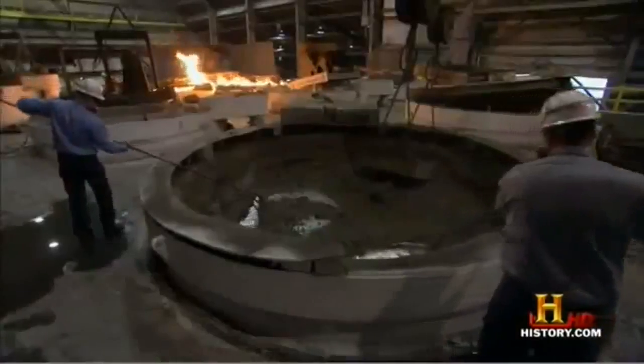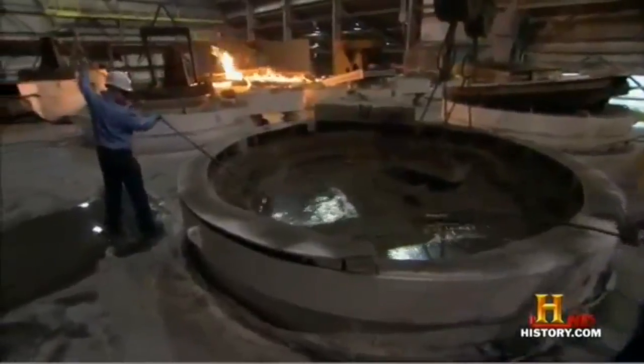We'll use chemicals such as sodium nitrate and sodium hydroxide to remove materials that we're able to oxidize out of the lead. Those materials will float to the top, and then we'll use our overhead crane and our operators to manually remove the dross from the surface of the lead. Once we've removed the dross, we basically have a pure lead alloy, which is ready then for further processing.